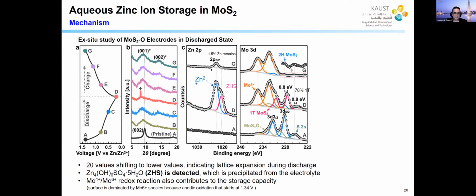There's a lot of side reactions. So we did this. This is a very common experiment in battery analysis. You do a discharge and you do a charge. You make 6 or 7 or 8 batteries, and at different states of discharge, you take the battery and you analyze it. So here the pristine battery, and this is the battery after you discharge it.